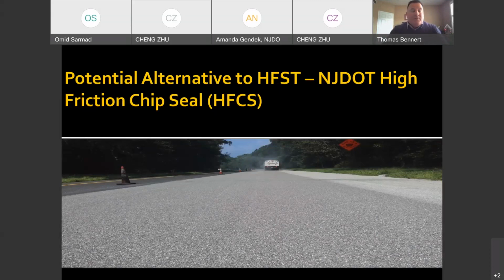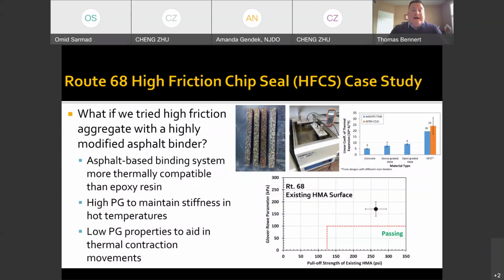And the way that asphalt binders are currently being developed, we can utilize a number of different polymers and methods to essentially create a fairly good bonding agent that is asphalt based. So now we have the compatibility between the asphalt binder and the pavement, or the bonding material and the pavement surface, that we didn't have with the traditional HFST. This brings us to Route 68.